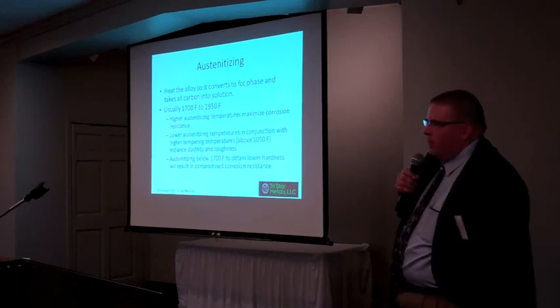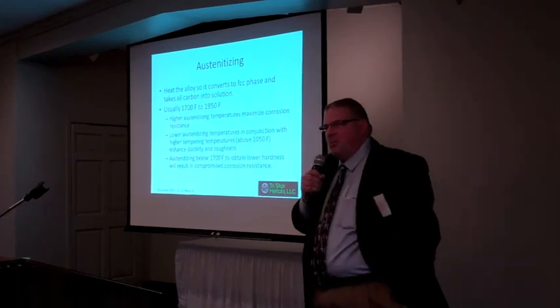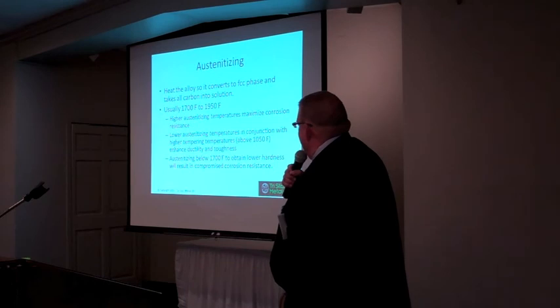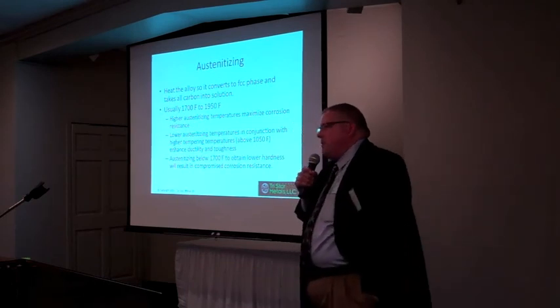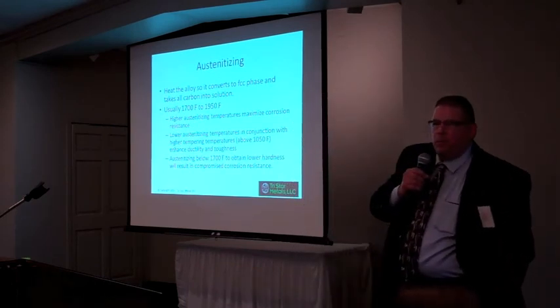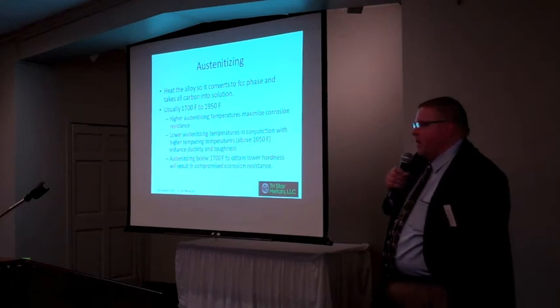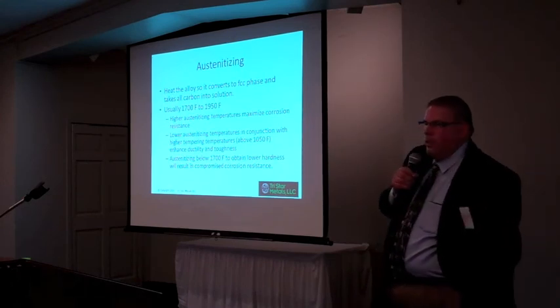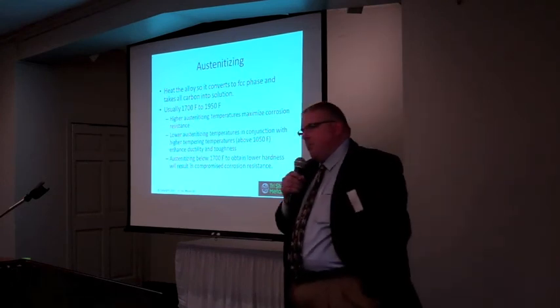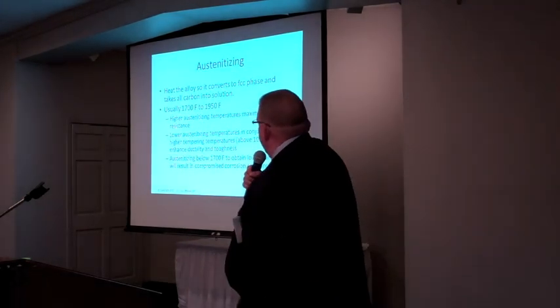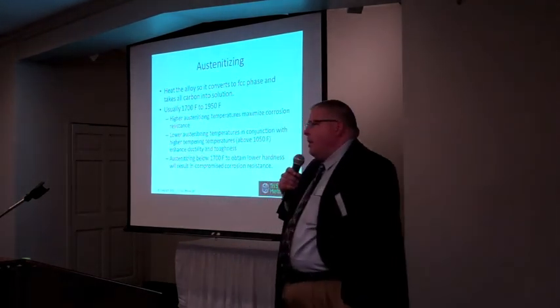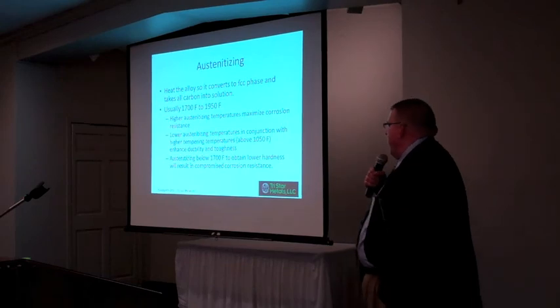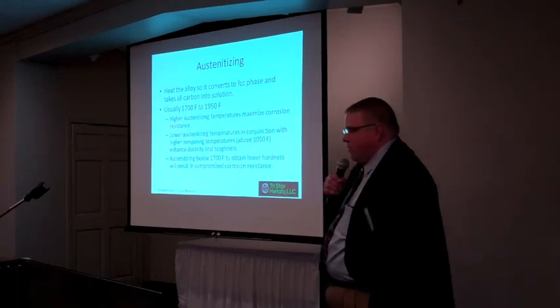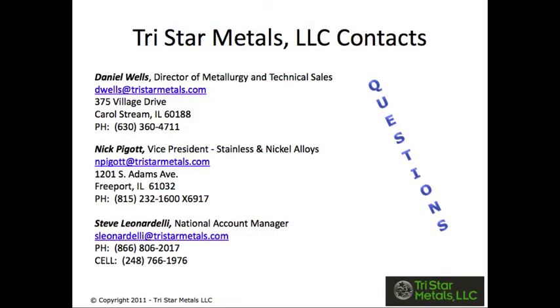Some heat treaters will, and I don't speak for any heat treaters in particular, but I've run into instances where customers have asked for an alloy to be used out of its normal hardness range. For instance, Trimrite used in the low 40s Rockwell. It's just not designed to be used there. So what they'll do is they'll austenitize slightly lower to get the hardness down and temper high, and that does compromise corrosion resistance, and in some cases stress corrosion cracking resistance as well.